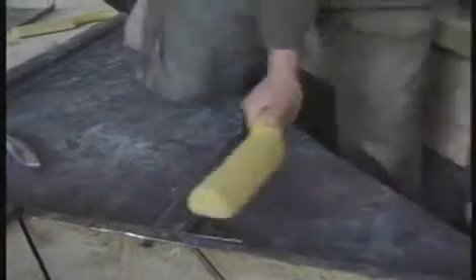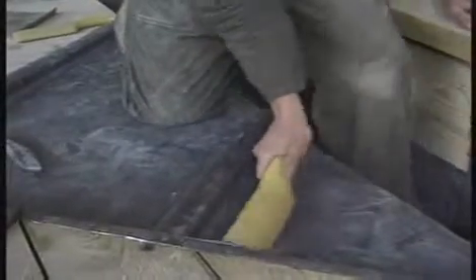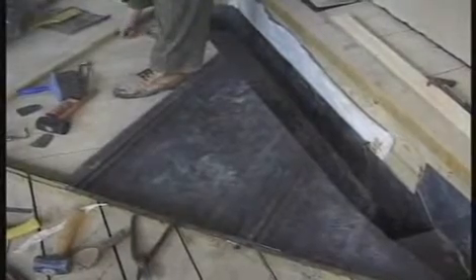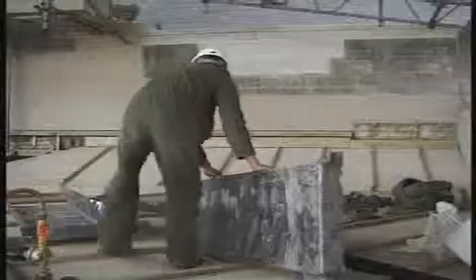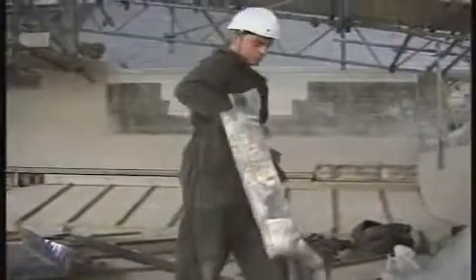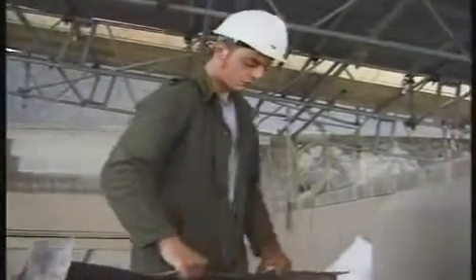Lead is a highly durable material protected by a naturally forming surface layer of lead sulfate. As it slowly forms, this patina can wash off, staining other materials below. This problem can be overcome by a smear coating of patination oil.